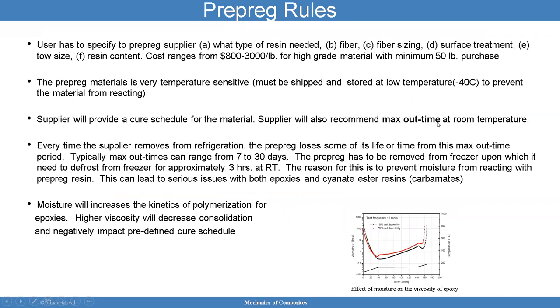And that's very important for these applications, to make sure that we're not violating this max out time. Because if you violate the max out time, the resin may not perform as intended. Every time the supplier removes it from the refrigeration, the prepreg will lose some of its life. That's the bottom line. So if you take it 2 times out, it's going to be different when you take it 10 times out. And if you take it 10 times out, you can expect a life reduction from the max out time period. A typical max out time can range anywhere between 7 to 30 days. And how you come up with this, the suppliers do a tremendous amount of testing to determine those inputs. Okay, that's the way it works.